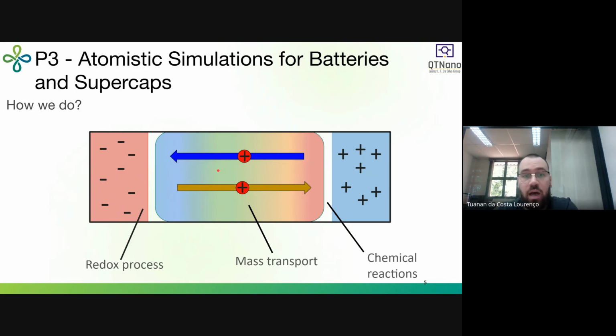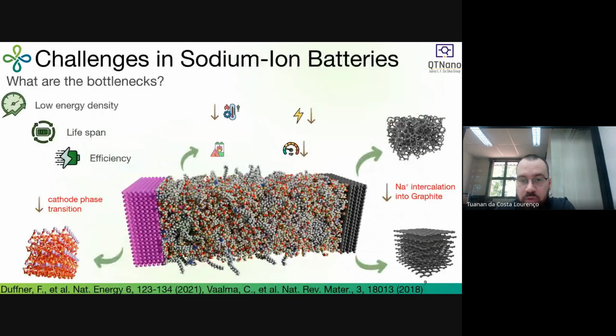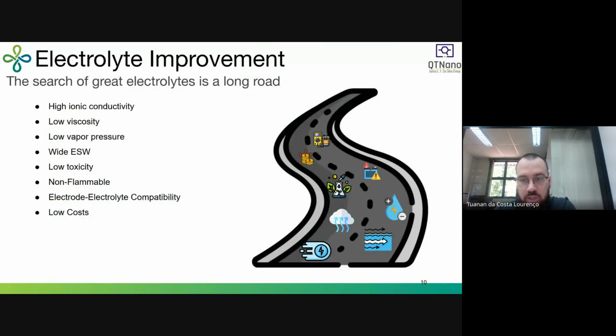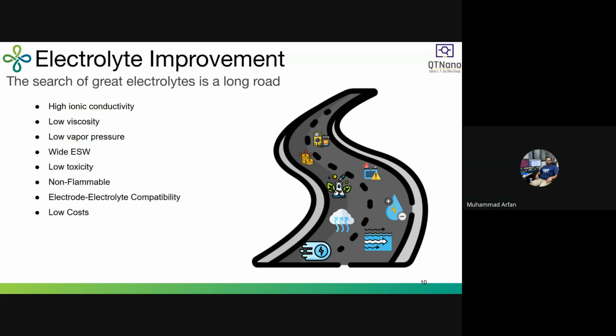However, if you have an ionic liquid with lower conductivity than this previous one, but in which you can have more and more sodium ions, and these sodium ions can move better than in the other systems, then you have a good system. So when you think about charge transport in the electrolyte, you need to think about the overall charge transport and also the charge transport that comes from the alkali metal ion. Is that okay? Yeah, thank you.